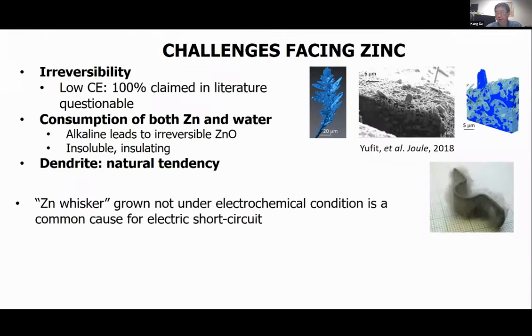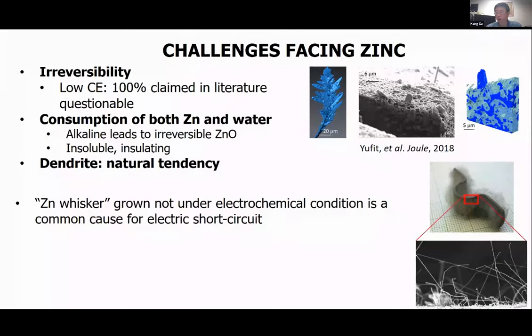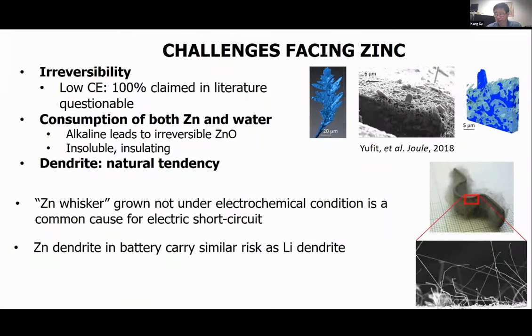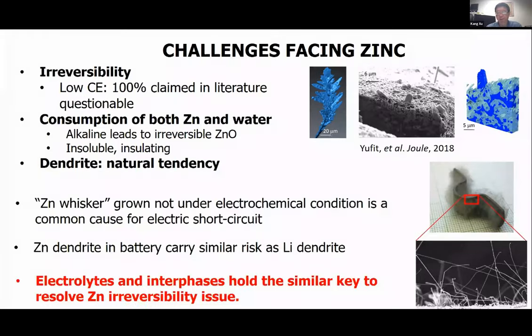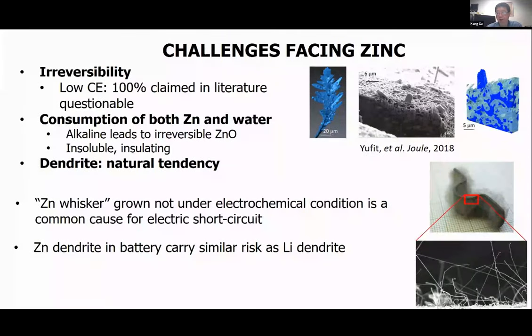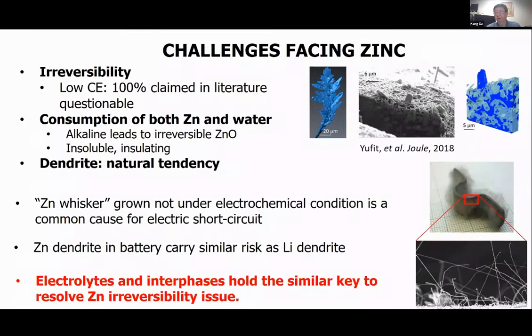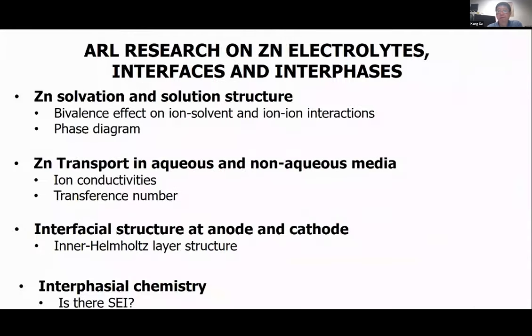Even in a non-electrochemical environment, such as electronic boards, zinc still grows such things like zinc whiskers. That's a major reason for most short circuit incidents in electronic boards. So to resolve this key issue, we have to study how the electrolyte and the interphases play a role in suppressing or promoting zinc dendrite growth, and how we can improve the reversibility of the zinc metal anode.